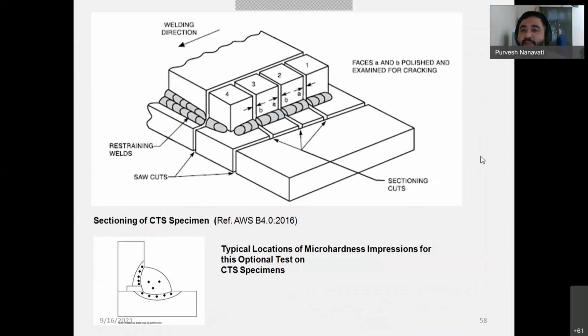In this way you have to quench the test specimen. Then you have to section the specimen 1, 2, 3, 4, and examine these facing sides A and B. This gives you a picture, an idea about the sectioning of the specimen. After sectioning, you can also go for micro hardness measurement in the weld metal and the heat affected zone, particularly because this is a fillet weld joint, right? So you would examine this specimen for microstructure and micro hardness.